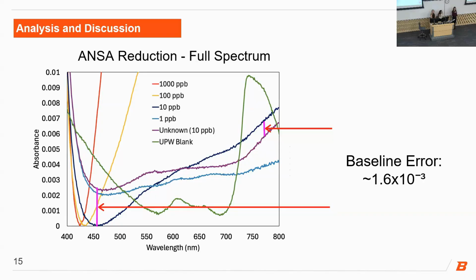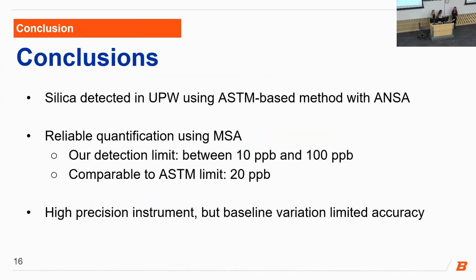While we're not sure of the exact cause of this baseline variation yet, we think that it could be due to scattering, because the instrument is agnostic as to whether the reduction in intensity of the light is due to absorbance, scattering, or refraction. Different things may be able to cause different scattering in the sample, such as different speciation during the silica molybdate blue complex development.